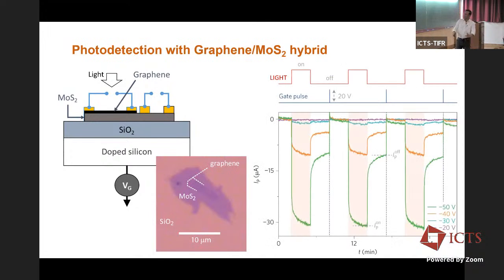Okay, now what happens is very interesting. This is experimental data. You can see when the light is switched on, the current through graphene immediately drops by a very large amount, about 30 microampere. And when the light is switched off, it returns almost fully, but then you give a little bit of a voltage pulse on the gate to get it back to the original value. Now this is very important. This essentially is a conversion of light into electricity. The light comes and the change in current takes place. And this can go on forever as long as you keep on repeating this cycle. What was interesting in this was that the change in current was extremely large for a tiny amount of power of light.